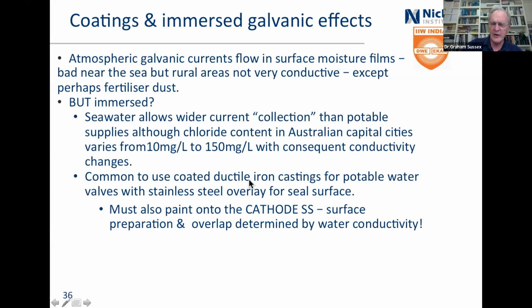Okay, now you look at that and you say, well, hang on a minute. Now you're coating the actual thing that you're protecting. And yeah, it's true. But you do that and you then put the overlay, or you put this paint onto the stainless steel surface as well, so that you have to have less of a throw through the water. And remember, we're talking about potable water. We're talking about reasonably low conductivity. Yes, and it works reasonably well.